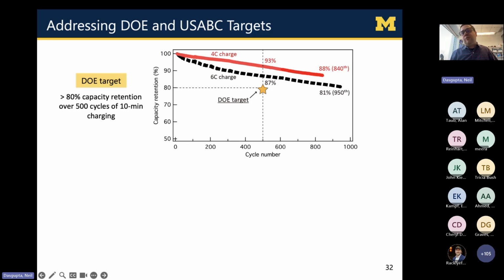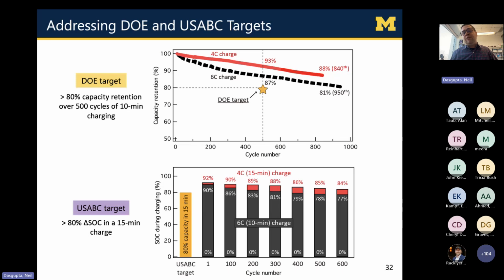So the DOE target was they would like to enable 500 fast charge cycles with less than 20% capacity fade. What we see is that with our whole electrode pattern, we can maintain 93% accessible capacity after 500 4C fast charge cycles, which is a really aggressive charging condition. That's much faster than going to a supercharger right now to recharge your battery in 30 to 40 minutes. And even at 6C, which is a 10-minute recharge, we're able to beat the DOE target. We're also able to exceed the targets of the US ABC.